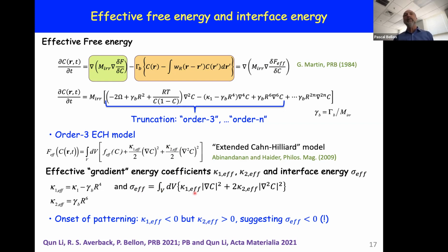The expression is given here. And the key point is that when we increase gamma, you can see that this term is positive. The phase separation is driven by omega, the interaction term. When we increase gamma, we reduce the driving force for phase separation. This is how we can express or rationalize the stabilization of a solid solution.